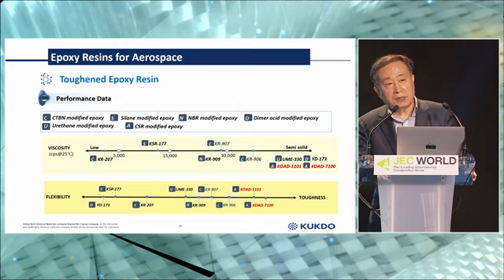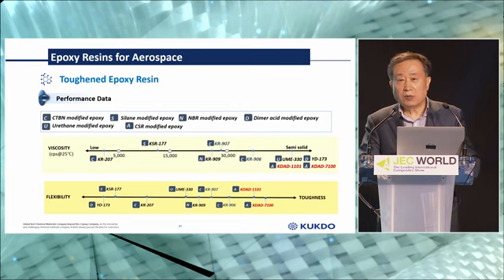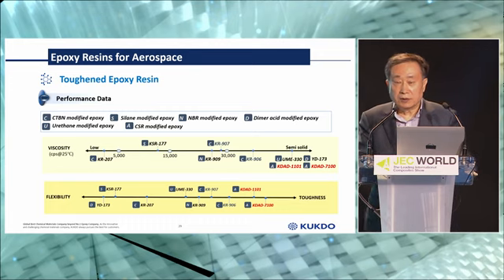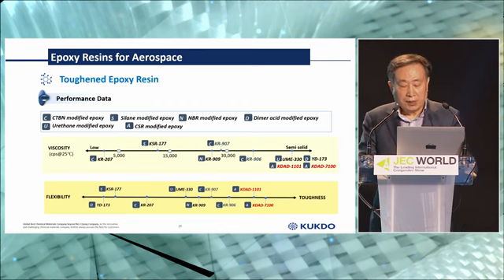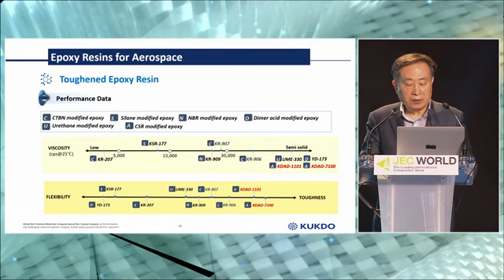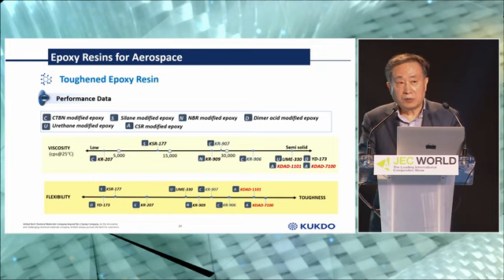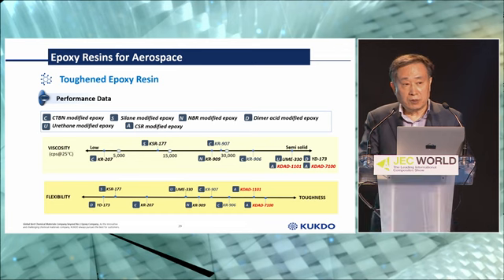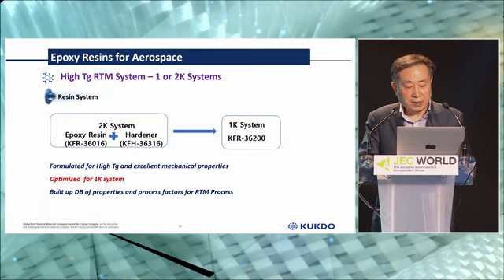And for aerospace, not only heat resistance or low temperature resistance, in many cases we need micro crack resistance. So we have to have toughened epoxy. To reach those toughened properties, we can modify with rubbers, silicone, or core-shell materials. So as you can see, with the viscosity and the portion of the toughened materials, we can have different properties. Details, if you have questions after my speech, you can ask me separately.